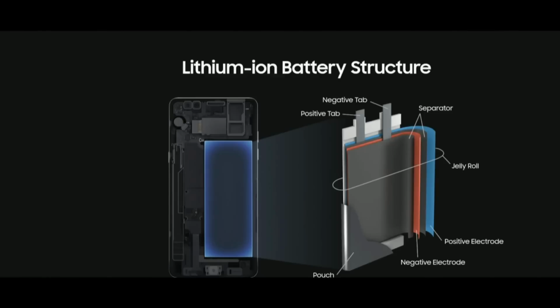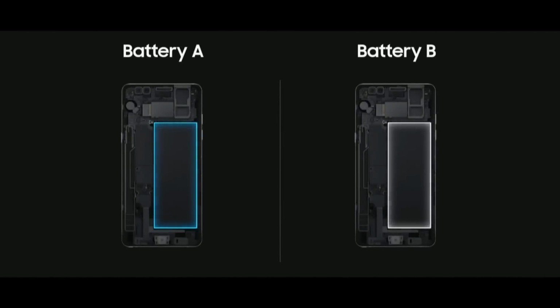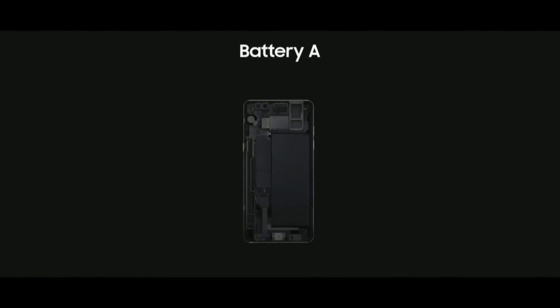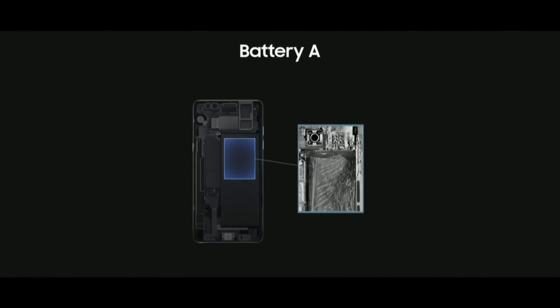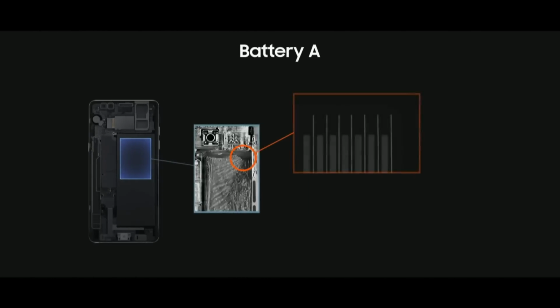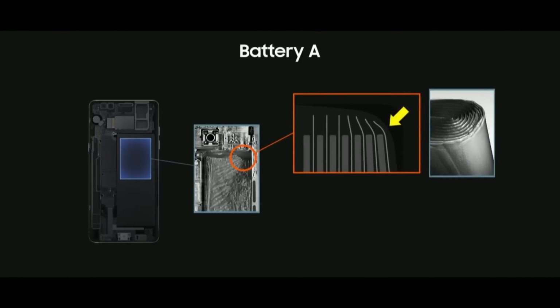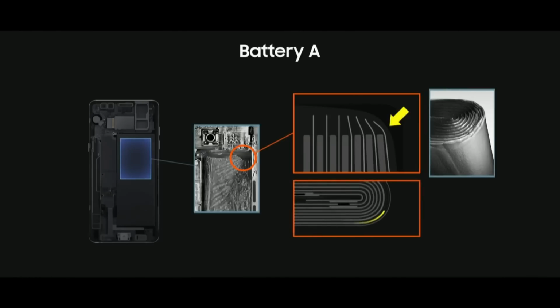Based on a detailed analysis of the affected batteries, both battery A from the first recall and battery B from the second recall, we identified two different factors. As you can see from the CT scan of battery A units, we found that the incidents consistently occurred in the upper right corner of the jelly roll. Our analysis showed the main cause for the incidents was deflections in the negative electrode. We were also able to confirm that some additional contributing factors, such as incorrect positioning of the negative electrode tip, led to a higher likelihood of incidents.